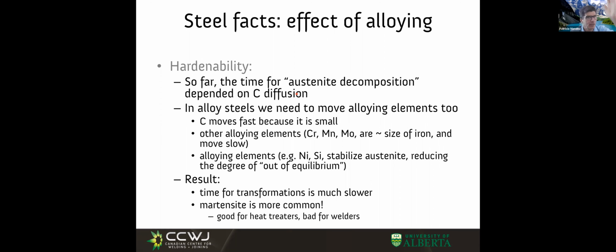When we go crazy all the way, quenching down to low temperatures, the carbon has no chance to diffuse out and is trapped and unhappy, and it distorts what would be a ferrite lattice, that is a BCC, into a BCT, that is body-centered tetragonal. So instead of being a cube, now it's kind of a prism, and it's very hard and brittle because it cannot deform.